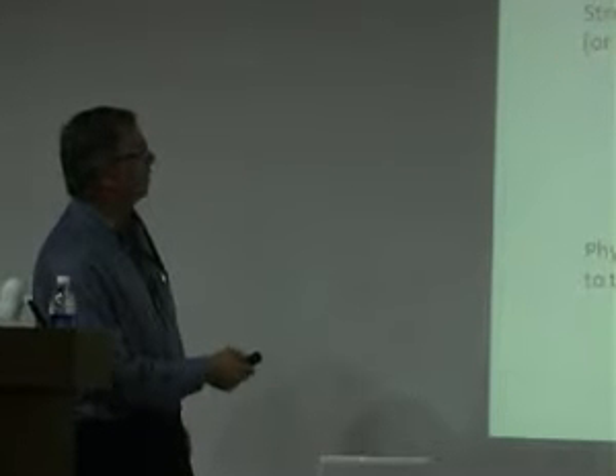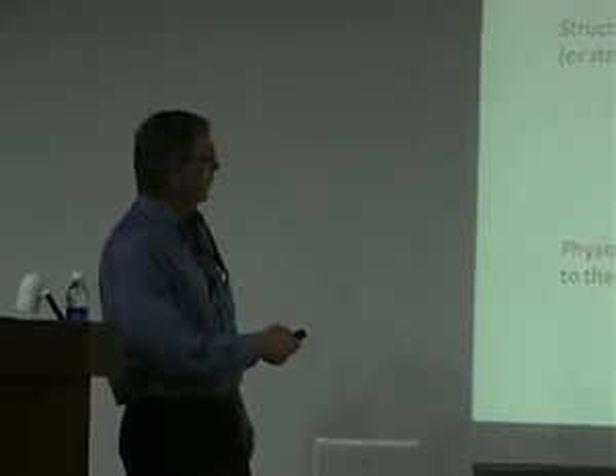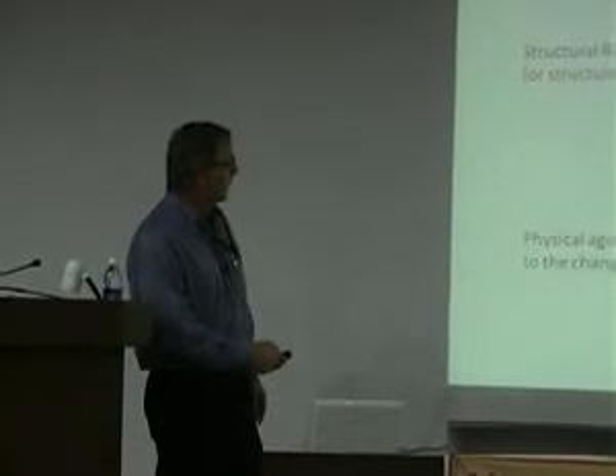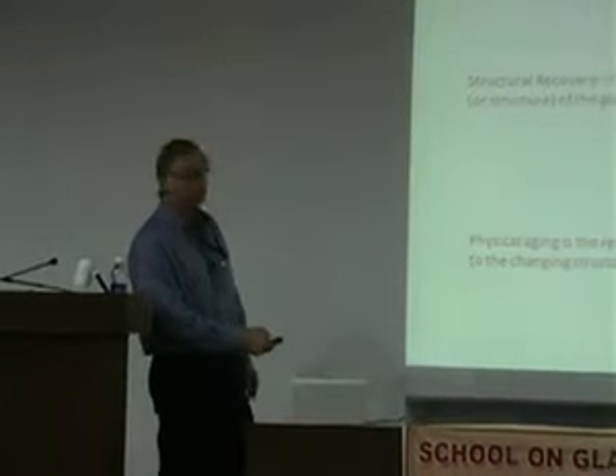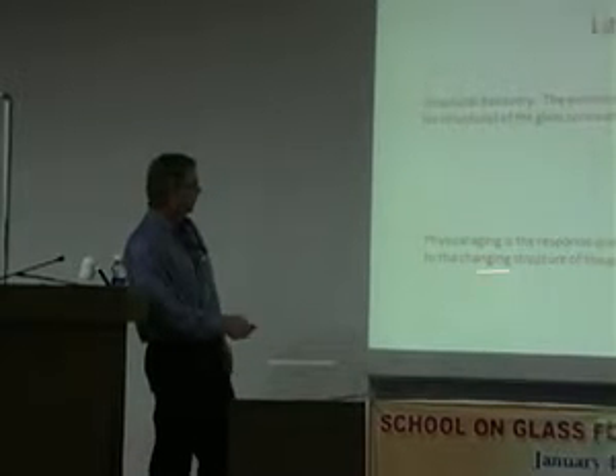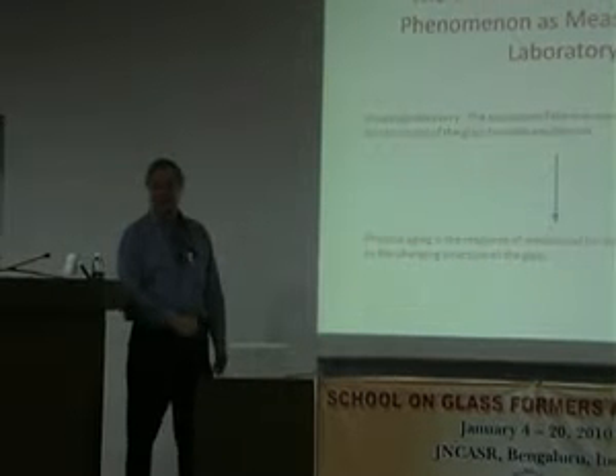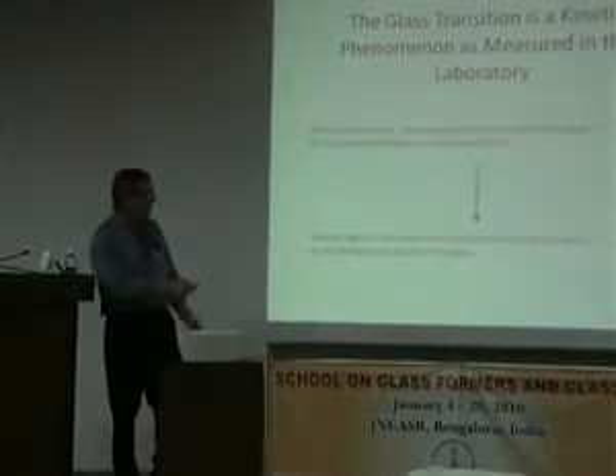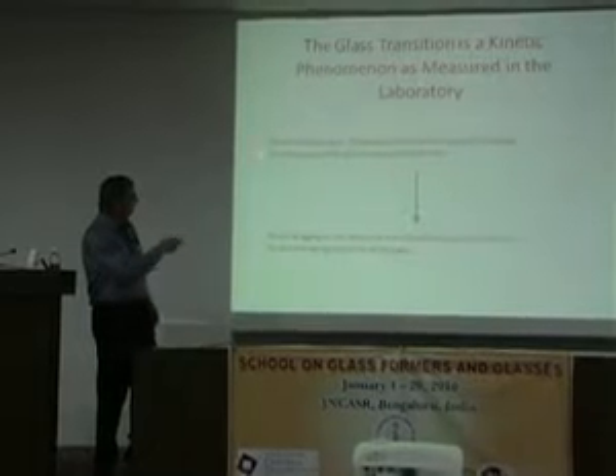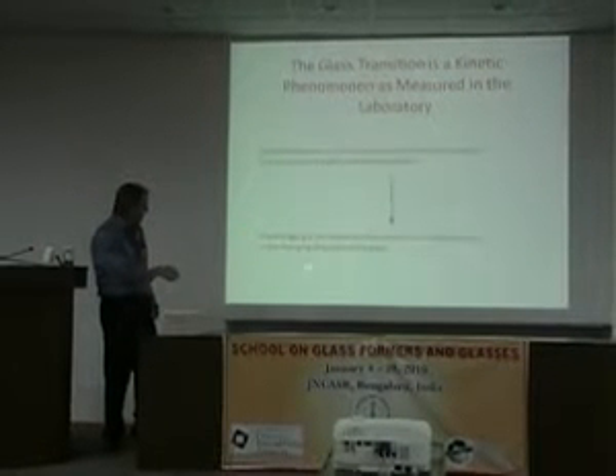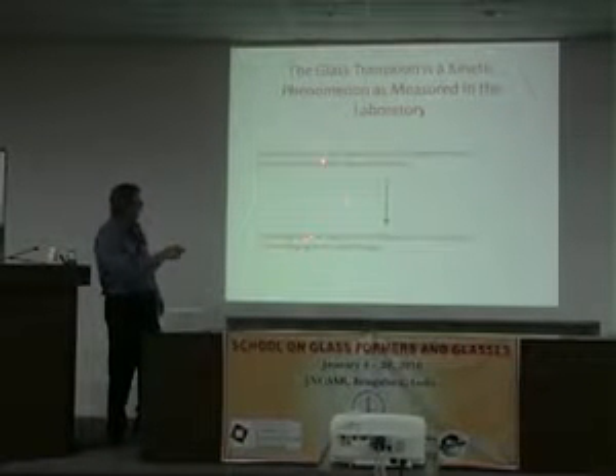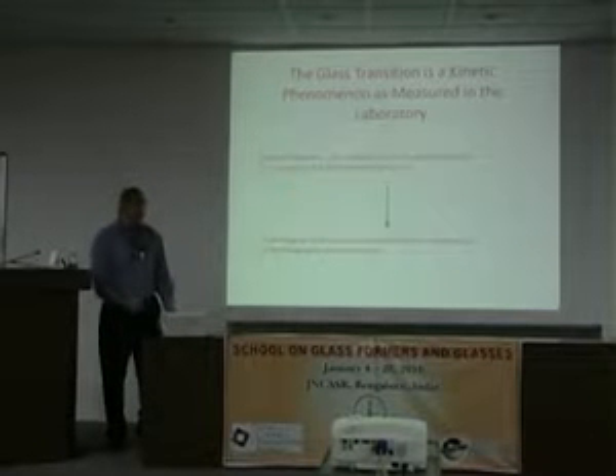So, as I just indicated, structural recovery is, of course, the evolution of the non-equilibrium state, such as volume or enthalpy, which we call the structure of the glass, towards equilibrium. And then physical aging is the response of the mechanical or other, as I said, dielectric property to the changing structure of the glass. So there's a slight subtlety. Some people call structural recovery aging, but in fact, the physical aging is the response to these changes in state, if you like.